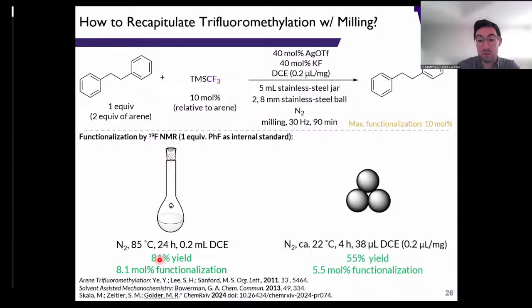Mechanochemically, we can run this for a lot shorter time in the ball mill using much less solvent, and we get still pretty good yield in about 5 to 6 mole percent functionalization. So they showed us that we could use these relatively unreactive arenes that are found in polystyrene just through the use of this bibenzyl model system. We then wanted to start to explore more relevant polystyrene substrates.